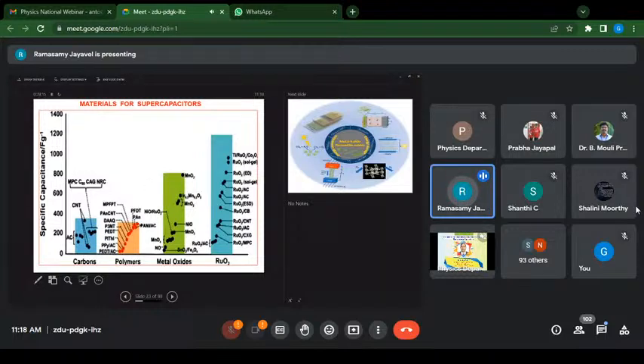And the combination of this, either polymers with the carbon or metal oxides with carbon, for example, ruthenium oxide as a base material, if we have activated carbon or CNT or carbon black, all these carbon-based materials can be integrated with binary metal oxides, so that the maximum specific capacitance can be achieved using this material. Okay, so there is a lot of scope for this material to be very effective and having very important application in defining the supercapacitors.